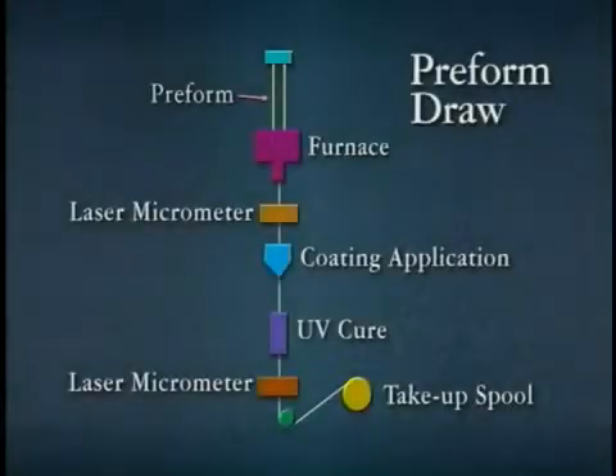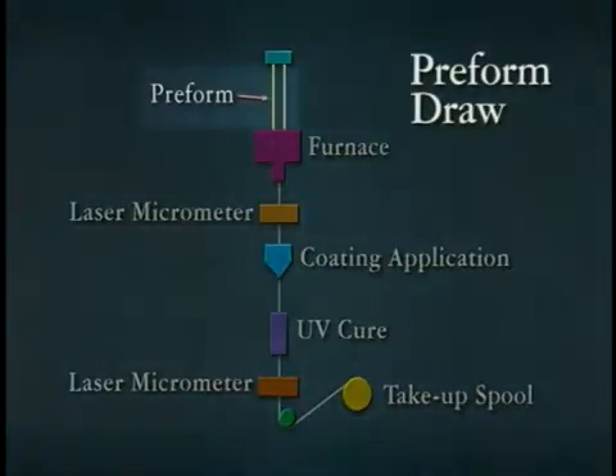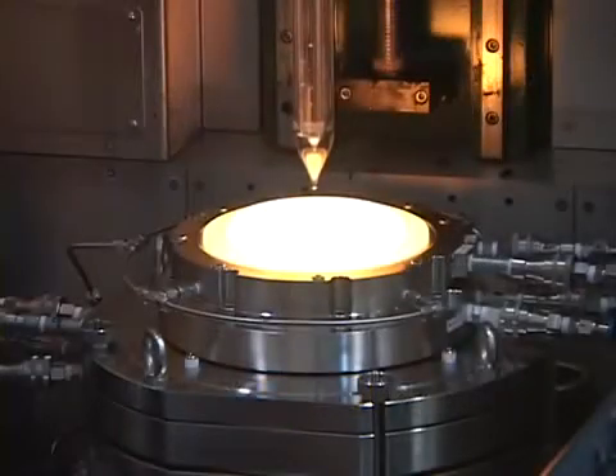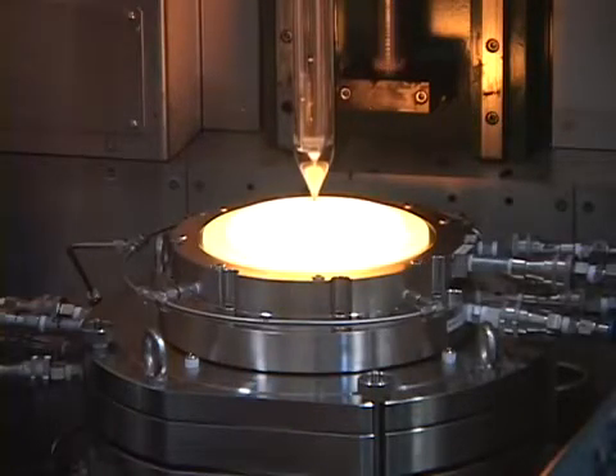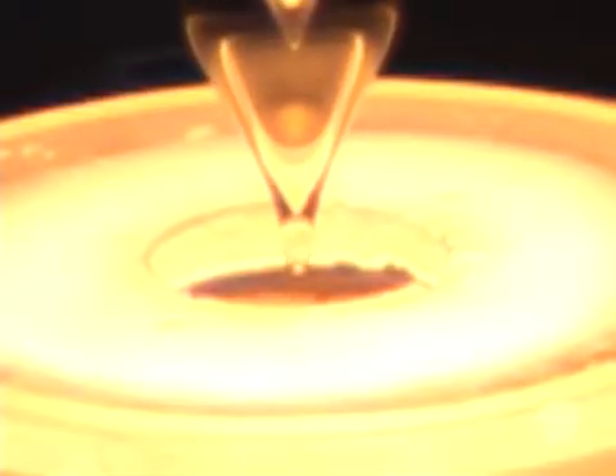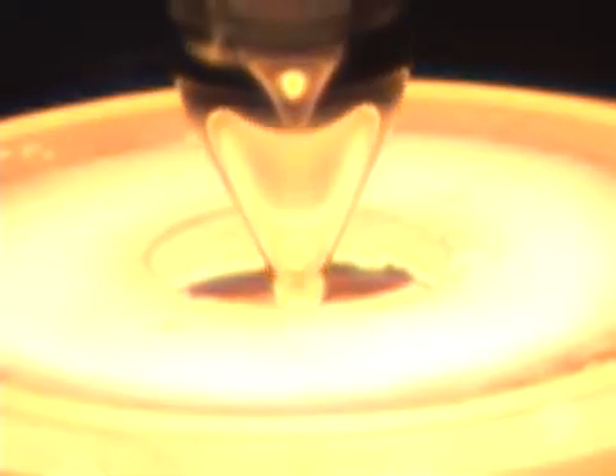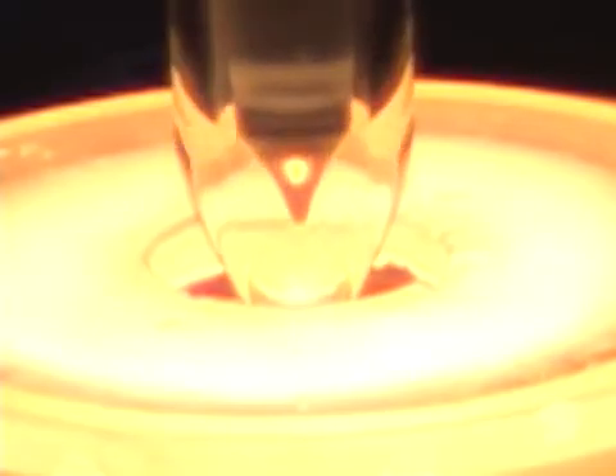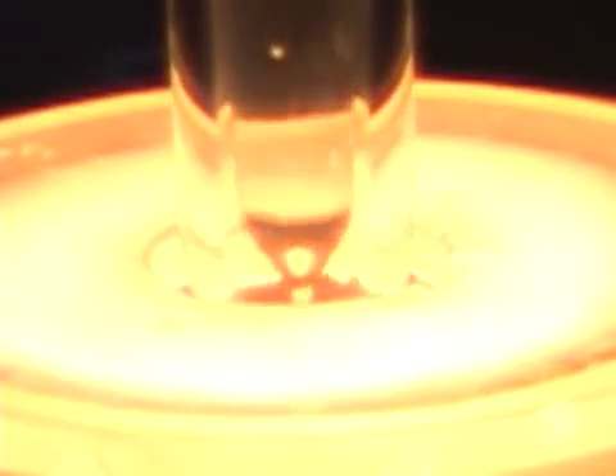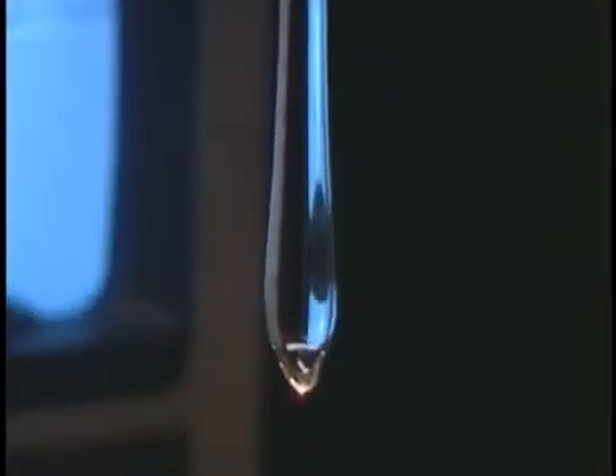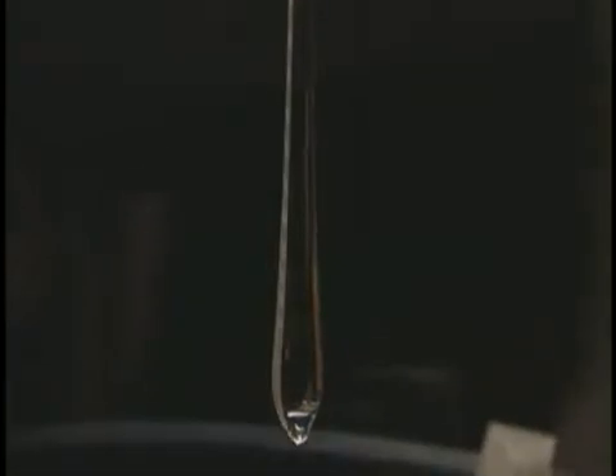Fiber draw is the process through which the preform is converted into optical fiber. First, the preform is lowered into a high-purity graphite furnace where tightly controlled temperatures approaching 1900 degrees Celsius are used to soften its tip. Then gravity takes over, allowing the molten tip to free fall, drawing a thin strand of glass from the preform.